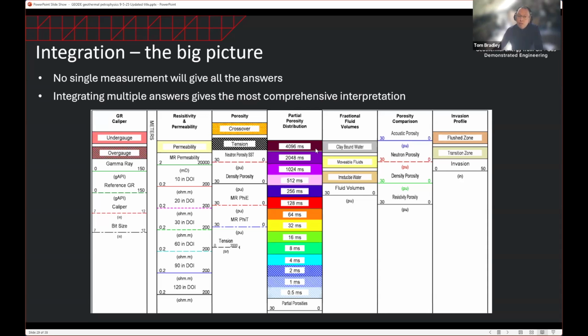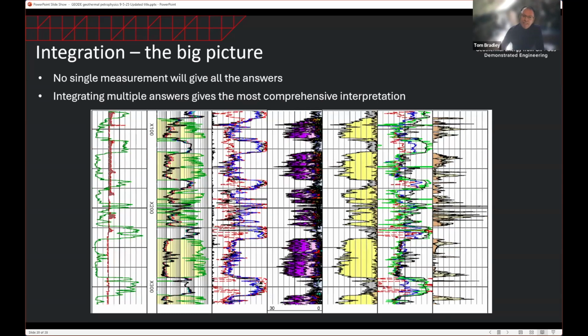This is a geothermal well that was logged recently, where we logged many measurements: resistivity, density neutron, nuclear magnetic resonance, and some other measurements that are not presented, things like sidewall coring and borehole imaging. By presenting the logs together, we can get a very good overview of this formation in terms of where our clean intervals are, where our shale intervals are, what our formation fluids in these clean intervals are. For example, low resistivity, telling us it's saline water. Again, going back to the NMR measurements, we have lots of movable porosity, very little irreducible and clay-bound porosity, therefore telling us high permeability by the red curve.